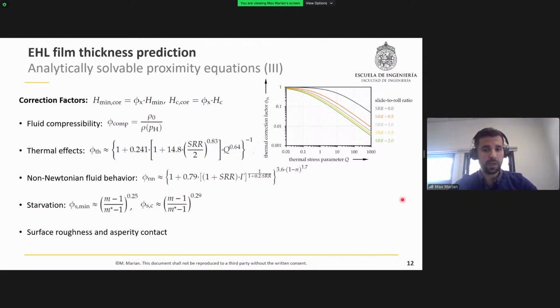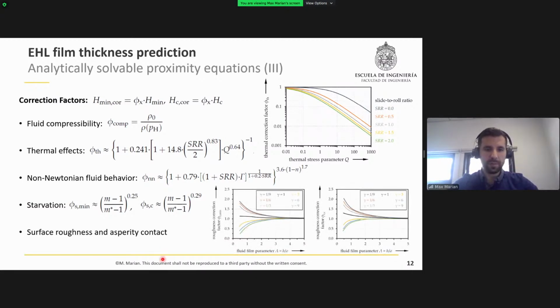Finally, it is well accepted that the surface topography, in terms of any kind of stochastic deviations from the smooth surface due to manufacturing, or also intentionally produced surface features such as surface textures or structures, has a decisive impact on the film formation in actual contacts. And basically, with decreasing lubricant film thickness, the impact of the surface roughness is getting stronger on the pressure buildup and also on the film thickness